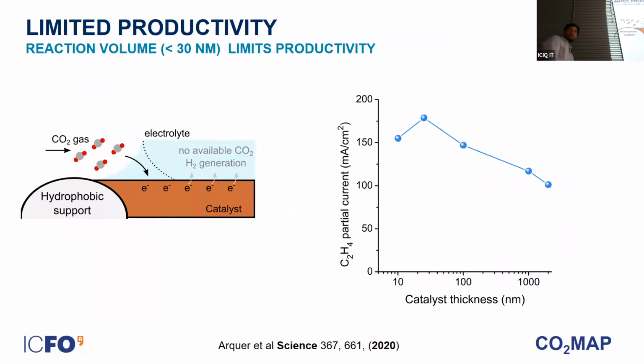So far we achieved stable operation. We have high Faraday efficiency for ethylene, and we have kind of high currents on the order of hundreds of milliamps, 150, 175 partial current density to ethylene, which is great, but it's not sufficient because we want to increase the productivity so that we can reduce the capital expenditures associated with this technology and make this technology viable.